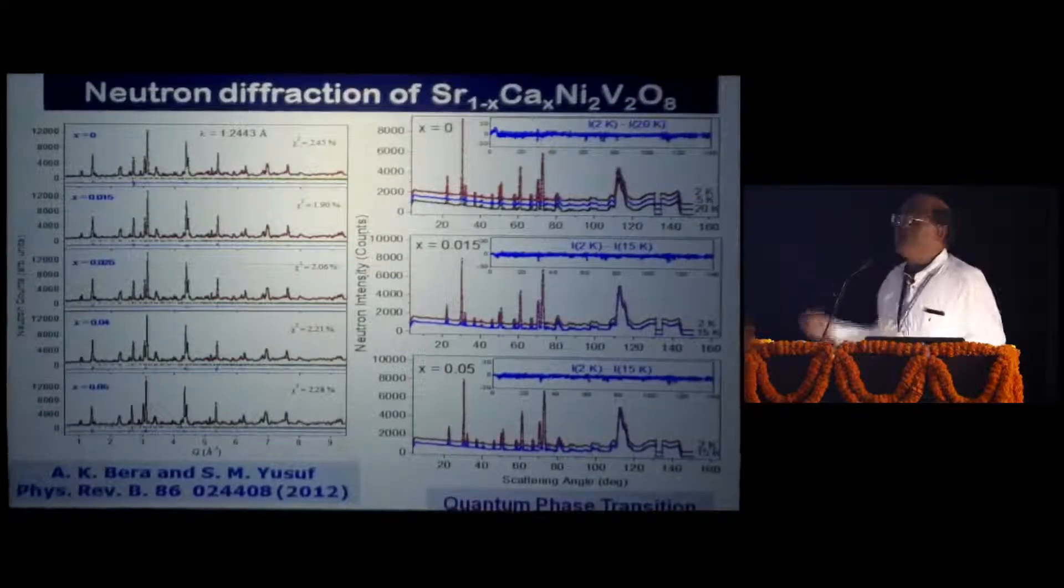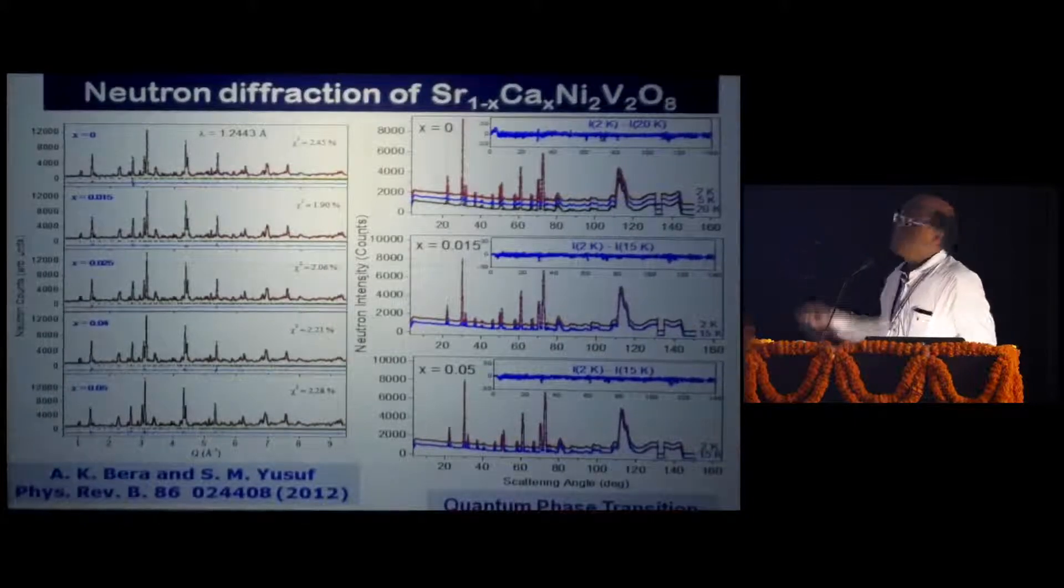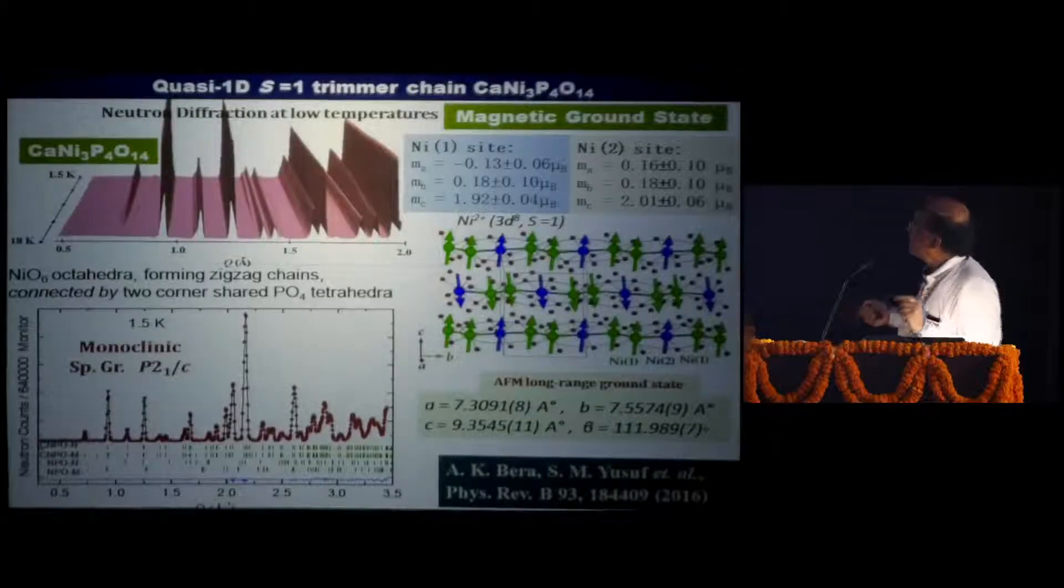This is the A lattice constant and the volume as you see decreasing by substitution, so the chains become closer, and that leads to the phase transition. We have established by doing DC magnetization as well as AC susceptibility with the frequency that indeed this is a spin glass state without any doubt. By doing neutron diffraction at the low temperature, we have shown the absence of any kind of magnetic ordering, what is expected for spin liquid as well as spin glass state, canonical spin glass state.